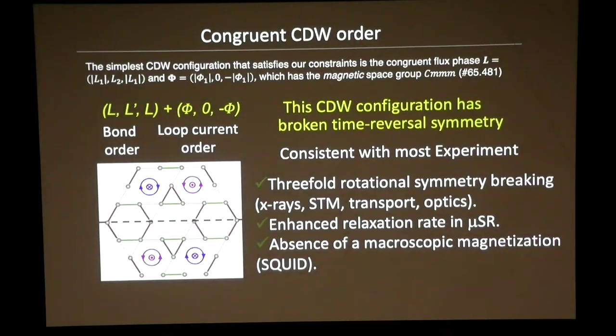Okay, so I think I'm almost at the end, actually. Essentially, using light as well as magnetic field, we're able to determine what the charge density wave in the system should look like. What light was able to do for us was to show that the CDW intensities actually have physical meaning, and also to show in a very clear way that the CDW intensity is directly tied to the amount of lattice distortion. And then we were able to use that information and go back to doing the magnetic field studies and establish that indeed time reversal symmetry is broken in this system.